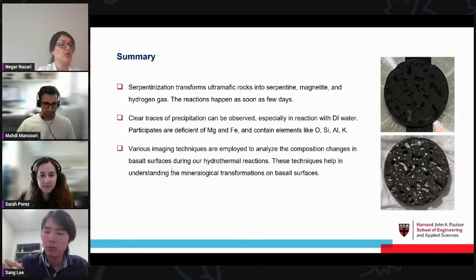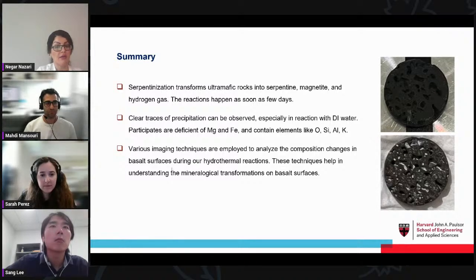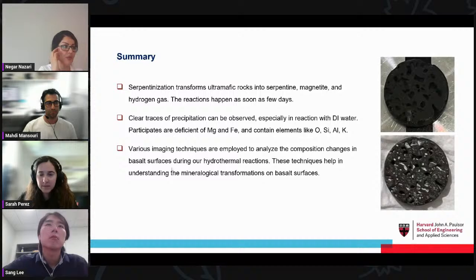So for the precipitant, we looked at the composition of the precipitates in the pores. They contain oxygen, silica, aluminum, and potassium, and they are deficient in magnesium and iron. So they could be some amorphous silica, or they could be some combination of clay. But what we are suspicious about is the silica that is actually generated, and the amount of the dissolution was so high that in 10 days we observed a huge amount of precipitation on the surface